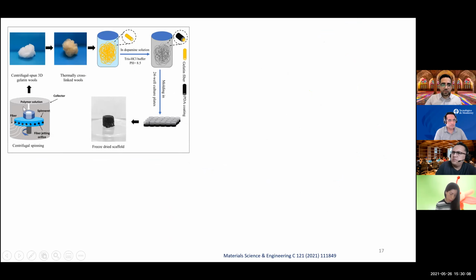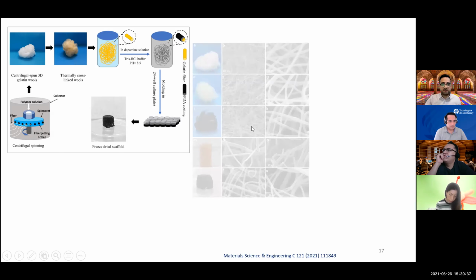The thing that I want to mention is the roadmap that we used to produce those kinds of scaffold. We use the centrifugal spinning and get some gelatin wools. After that, we do the thermal cross-linking, and then we put a thin layer of polydopamine on the surface because it has an extraordinary adhesion. We already mentioned that it can mimic the extraordinary adhesion ability of those mussels. And after that, we mold it in the well plate, and this is, as you can see, the freeze-dried scaffold, and it's a 3D scaffold.